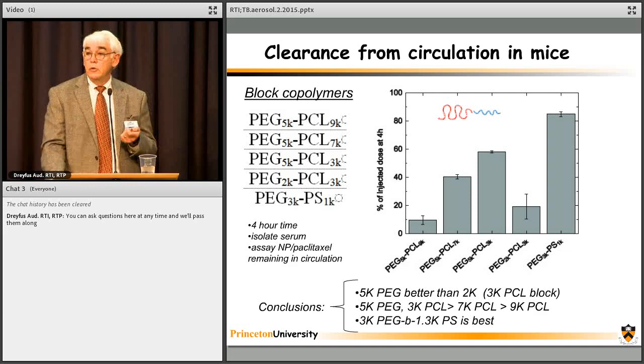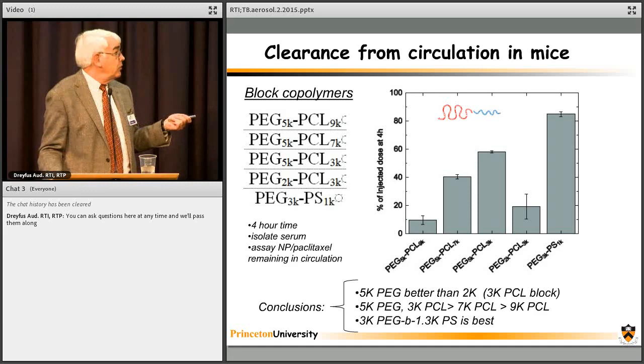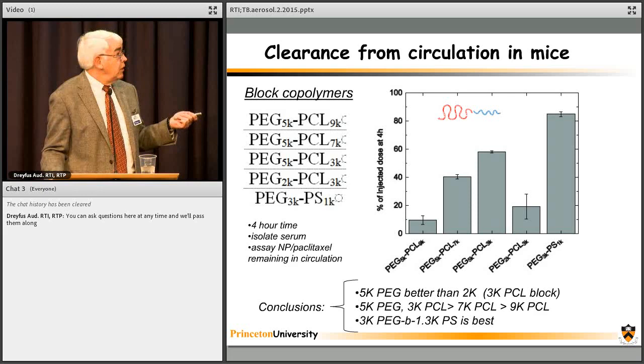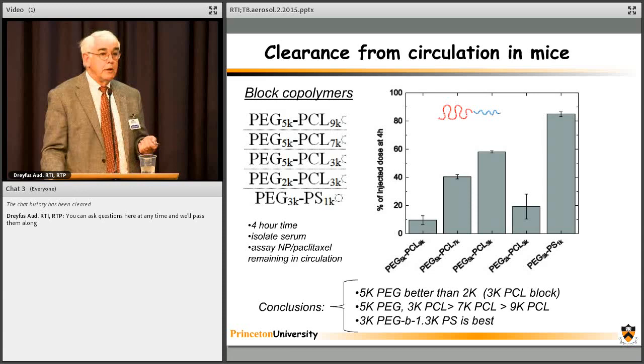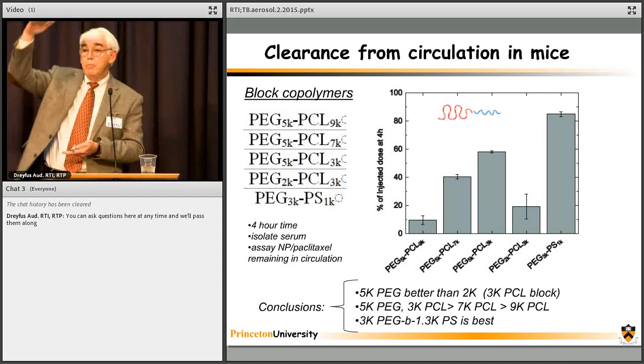And so we have two different kinds here, polycaprolactone. These are all polycaprolactone hydrophobic groups. That's polystyrene. And let's start here. So these are 2,000 molecular weight PEG and 3,000 molecular weight polycaprolactone. And this is 5,000 molecular weight PEG, 3,000 molecular weight polycaprolactone. What you see is the smaller PEG block is cleared much more rapidly. So it's not a thick enough, dense enough layer to prevent protein adsorption, and things are cleared. So a bigger PEG layer is better at preventing protein adsorption and clearance. So that's the first lesson.